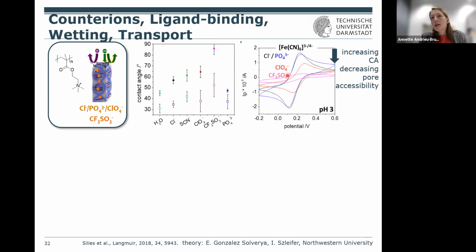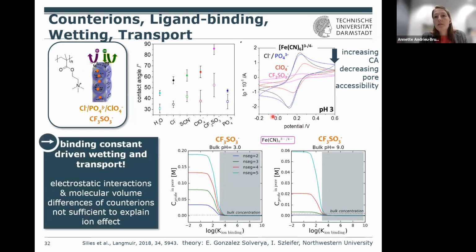And this then again relates to the transport that you see. So depending on the ion present, now you see almost the ion exclusion of the probe molecule. And again, with the Szleifer group, we did some theory, without going too much into detail, but we saw that actually this is ligand binding dominated, and depending on the ligand binding constants, you can achieve these effects of ion exclusion in these systems. So the message here basically is, if you do real separations and you have polymers and polyelectrolytes in the system, be careful on which ions are present.